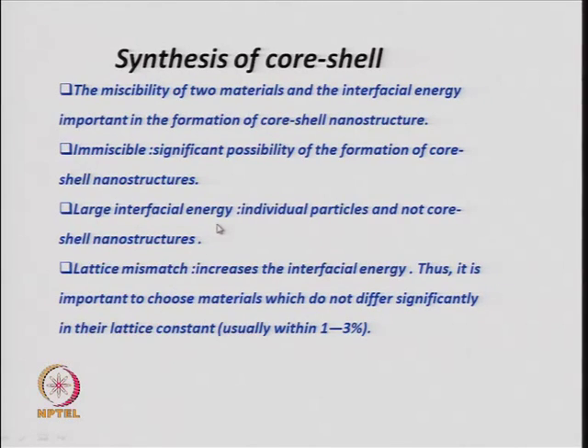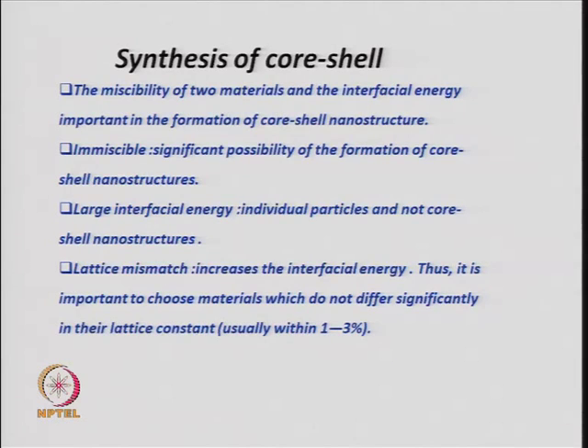Large interfacial energy is not good for core-shell nanostructures. Lattice mismatch — the difference in lattice parameters of materials A and B — also increases interfacial energy. Therefore you must choose materials whose lattice constants differ by no more than 1 to 3 percent. Large lattice mismatch makes it difficult to form a shell on the core, and you again end up with a composite mixture.